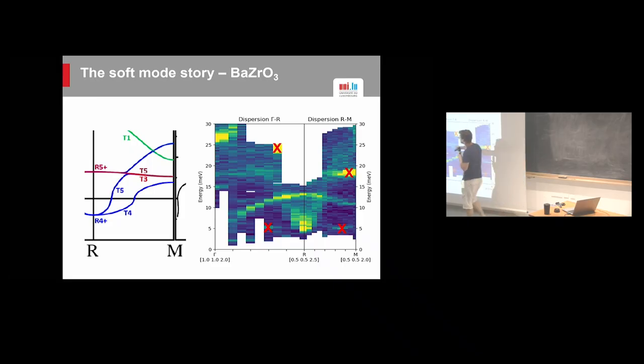Okay, this is going to zoom on the relevant part of the dispersion. Here you have a bit more. This is the acoustic branch, by the way, for those of you who are asking about the acoustics. And the mode that we see here and that we expect, of course, does not show up as negative, but it's here. So we can still see it quite nicely. All those crosses that you can see are what the neutron people call spurions. So it's absolutely not physical. It doesn't come from your sample. So that's why you can cross them out.